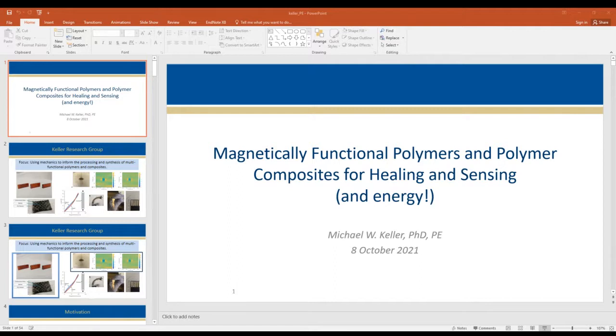So this little 1/2 inch by 1 inch long single channel specimen takes about 2 weeks to make, right? So I guess the take-home message is Keller's lab makes you do the same thing over and over again for very long periods of time. So that sucks. But this is really exciting, though. The thermal conductivities that we're getting on this are slightly above Inconel right now, and we're in the process of actually doing characterization as well.